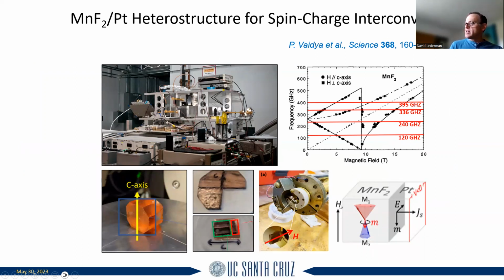You have the manganese fluoride. We apply a magnetic field like this, and then you should have a spin current flowing in this direction, and then that should create a voltage like this due to the inverse spin Hall effect. And so we tried different frequencies. These lines here are the resonant frequencies for the different modes. We tried 120, 240, up to 385 gigahertz.